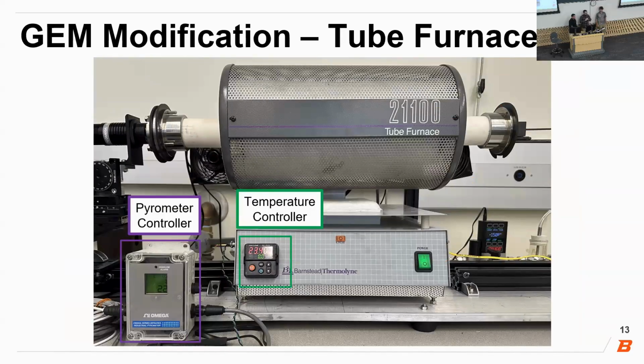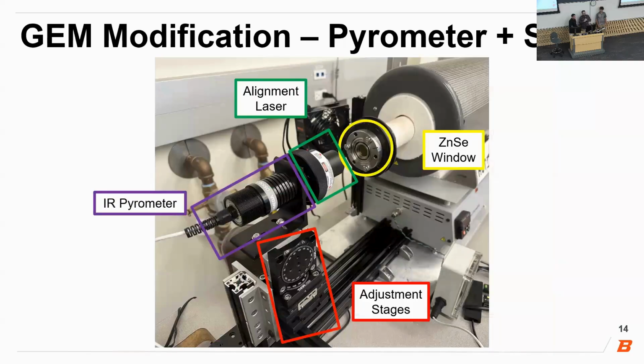To modify the tube furnace, we added a different temperature controller with dual TC input and RS-485 communication, as well as adding RS-232 communication to our pyrometer. The pyrometer is here, and you can see we added alignment stages to ensure precise and stable alignment throughout testing. You can also see an alignment laser to visually spot check where on the sample we are measuring infrared temperature.